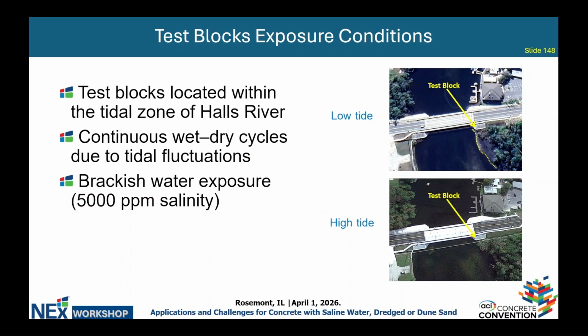At the low tide, we can see this is the test block after the 7 years. Here, the test block is partially dry, but here at the high tide, it's submerged. Another thing about the exposure condition is that the Halls River has brackish water with salinity of about 5,000 ppm, which can also introduce aggressive ions to the concrete structure that can interfere with its durability performance.